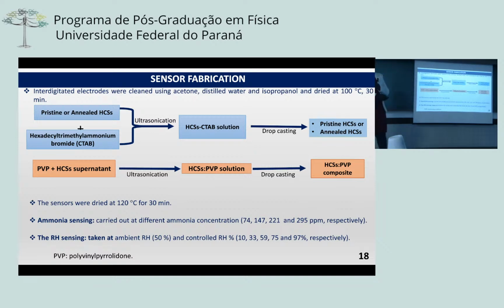The ammonia sensing was determined by varying the concentration between 74 ppm and 295 ppm, and the relative humidity was measured at ambient. At that time, it was very humid. It was during winter, 50%, and under a controlled relative humidity condition between 10 and 97%.